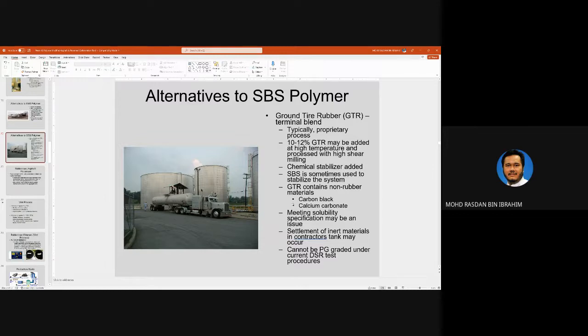Another thing is sometimes if you are using coarser, larger rubber particles, when you test it for penetration test, the result can vary quite significantly, because in one test maybe the needle punches on the bitumen and it hits the rubber particle, and in another test it does not hit any rubber particle. So the result can be quite confusing. That is in the case if you are using larger rubber particles. But if they are smaller, then it's okay.